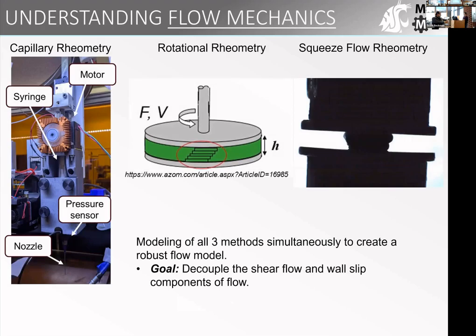So to characterize flow, we are using 3 different experimental methods. We have capillary rheometry, which is the most closely related to 3D printing, because we're using our print head and extruding our material from our nozzle and extracting pressure flow rate relationships. We're also doing rotational rheometry, where we have our ink squeezed between 2 plates and we shear it, we rotate the material and shear it. And we also have started doing squeeze flow rheometry. This is new, where we have our material that we are compressing between 2 plates and extracting the change in diameter as the material compresses.